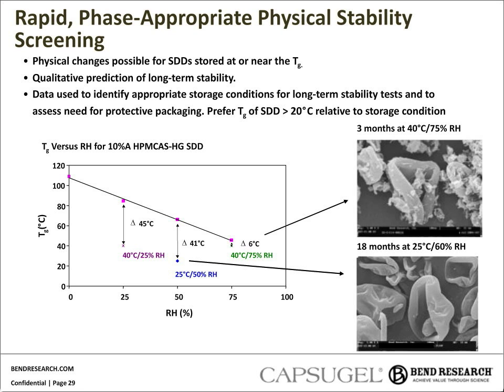So with modulated DSC, some of the first tests we'll do with formulations is evaluate the glass transition temperature of a dispersion as a function of relative humidity. And we'll relate this to potential storage conditions that the sample might see, and then use that as a guide to say, do we expect we're going to have an issue with this dispersion at some of the relevant ICH storage conditions. So in this plot, we're looking at the glass transition temperature on the y-axis, and on the x-axis is the relative humidity at which it's stored. So you can see how as water plasticizes the dispersion, and we increase the RH, the TG of the dispersion is going down. And what we're showing here is how it relates to different ICH stability conditions.